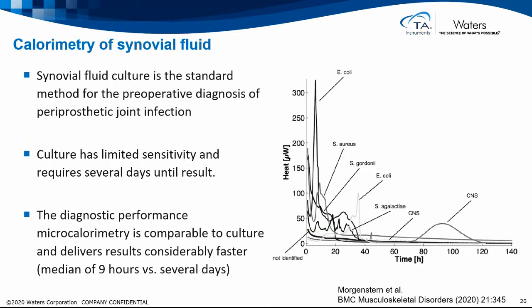This example shows calorimetry of synovial fluid. Synovial fluid culture is the standard method for preoperative diagnosis of a joint infection. But culture has limited sensitivity and requires several days until the results. The diagnostic performance has also been tested with microcalorimetry, and it's comparable to culture, but it delivers results considerably faster. The median was 9 hours versus several days in this study.